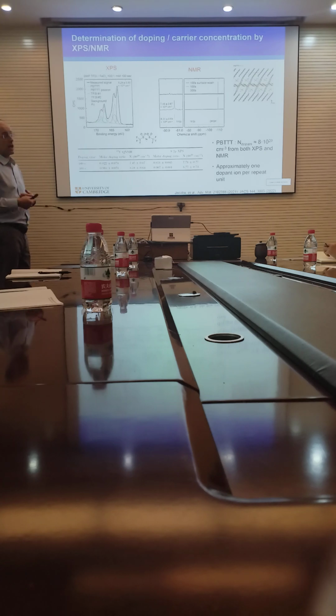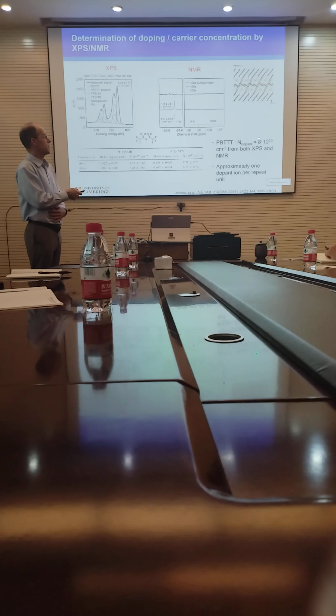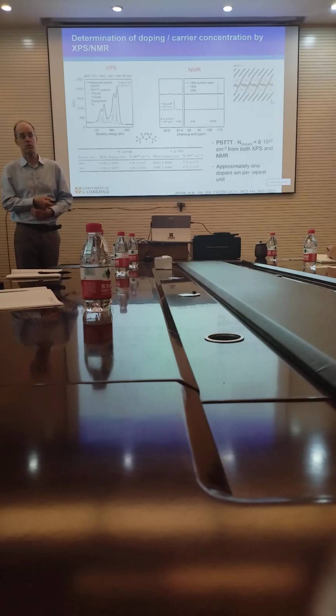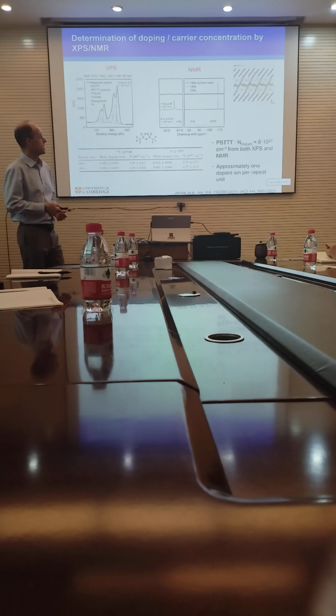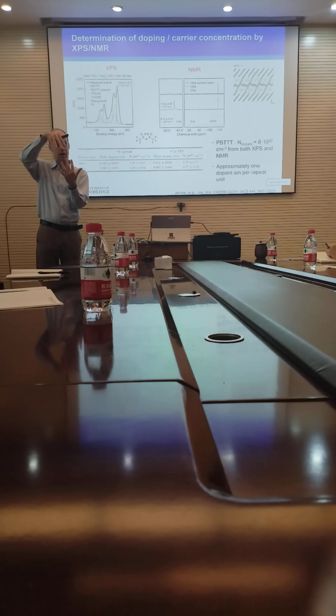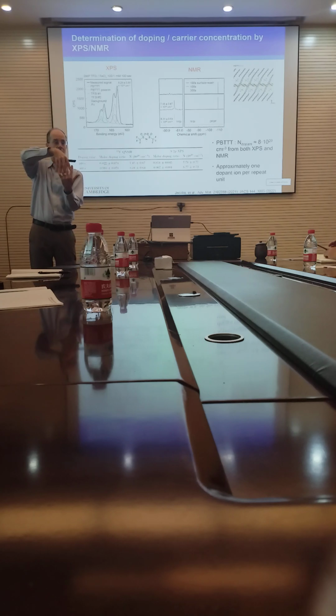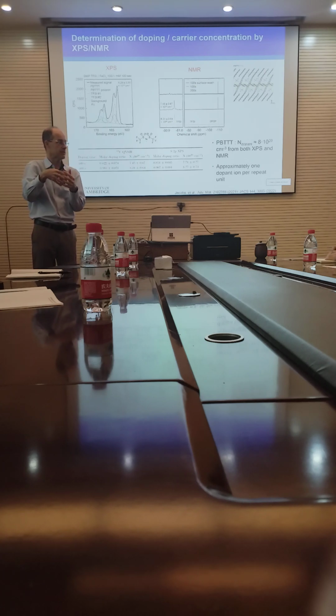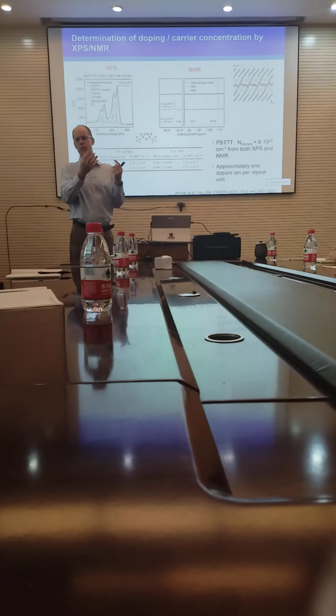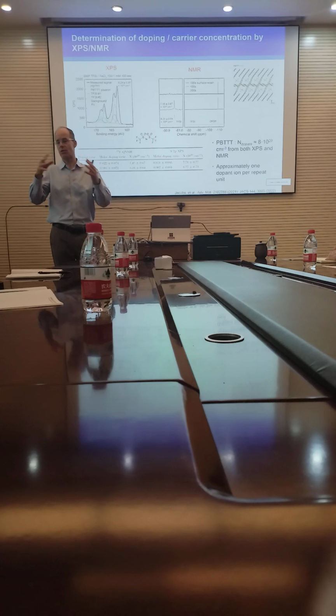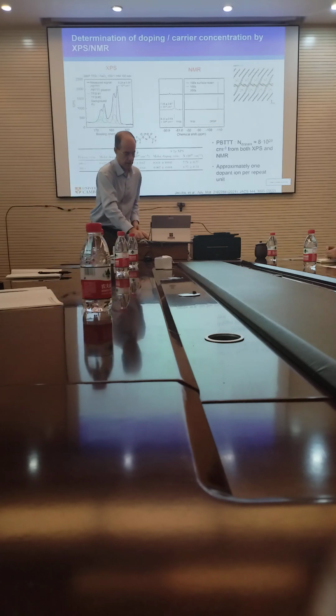And what we find at the highest doping levels in PB-T is a doping concentration of 8 times 10 to the 20 per cubic centimeter, and that essentially corresponds to this structure. In every cavity, you have a molecular dopant sitting. So you have essentially one charge per repeat unit at the highest doping levels. So that's why it's a beautiful model system. It's highly ordered. You have essentially exactly one charge per repeat unit.